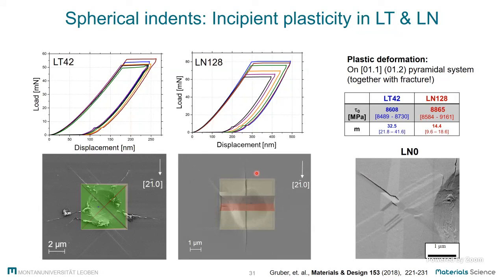But my question is, regarding the grinding process, we know the biggest problem is always the brittleness of the materials at room temperature. Is it possible to perform some high temperature grinding? Because that actually might help to induce the surface dislocations, because we know the yield strength is much, much smaller at higher temperature. Would that be useful or possible? What would be your opinion?